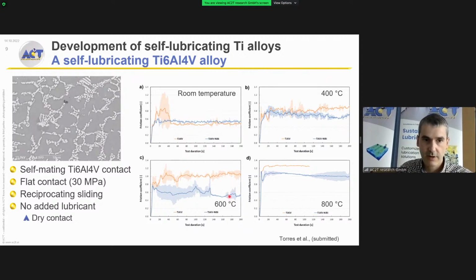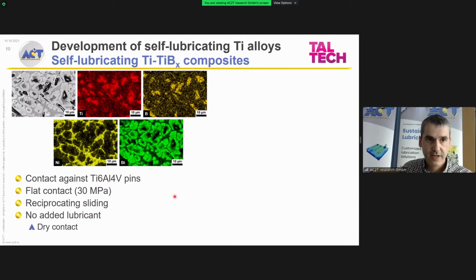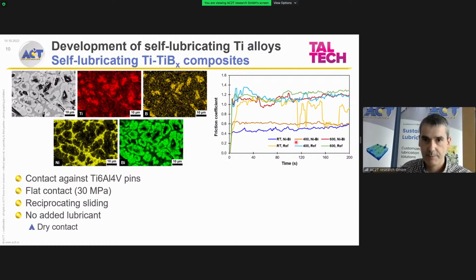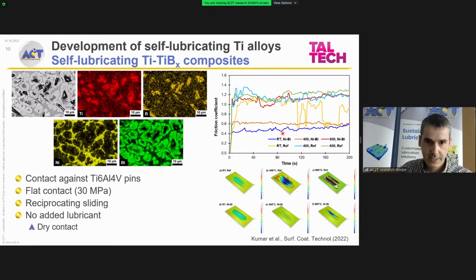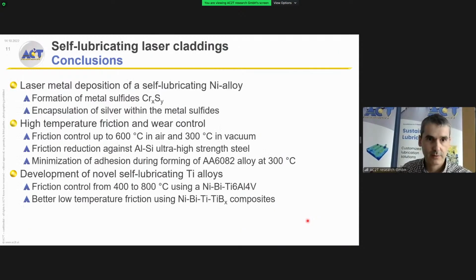And the best conditions for this self-lubricating titanium alloy is at 600 degrees, where we get a coefficient of friction relatively good and low at around 0.5. Again, self-mating titanium alloy without any lubricant at all. And finally, we came to our colleagues from Tallinn. They are working in this powder metallurgy, developing titanium boride composite materials, and we apply also this nickel bismuth addition, and we ended up having this titanium boride phase surrounded by bismuth, and this bismuth phase is surrounded by nickel. And we repeated these experiments, also very detrimental conditions, self-mating titanium contact, and we see that in this case, especially at the lower temperatures, room temperature and 400 degrees, friction in a titanium self-mating contact can be as low and steady as 0.4. And not only friction gets better, but also compared to the self-mating titanium contact, the wear becomes also much better.